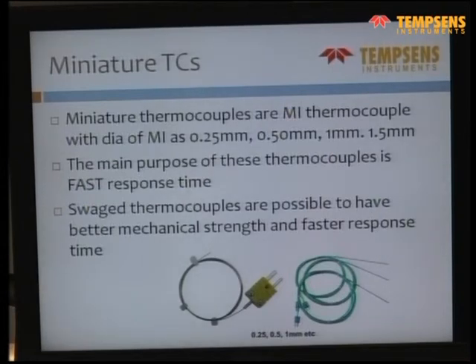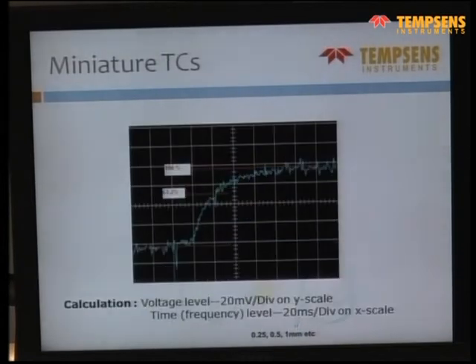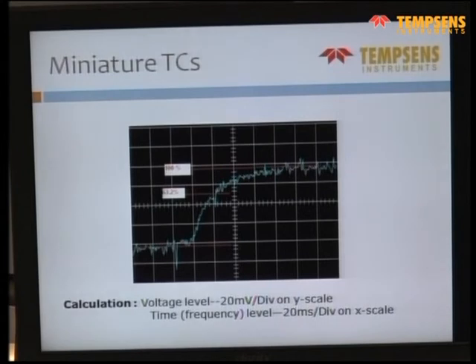Miniature sensors are available right from 0.25 mm diameter. So the wire would be only 0.04 or 0.03 mm, and you can have a response time of about 30 milliseconds with such a thing. Also, swage thermocouple means the tip would be narrowed from the bottom so that it gives better response time.